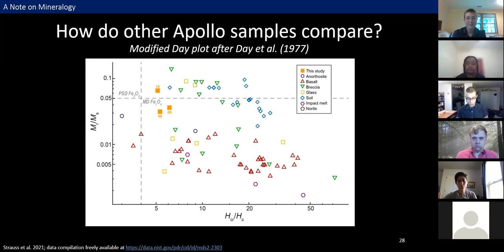So what we built is, to our knowledge, the largest published compilation of hysteresis parameters from Apollo samples to date. Each data point that you see here represents one sample or subsample from literature, sorted by bulk rock type as kind of a first pass. And the data from our study is shown in orange squares. I've also included these gray dashed lines, which indicate domain state regions from the original Day plot that are sometimes used to calculate grain sizes.